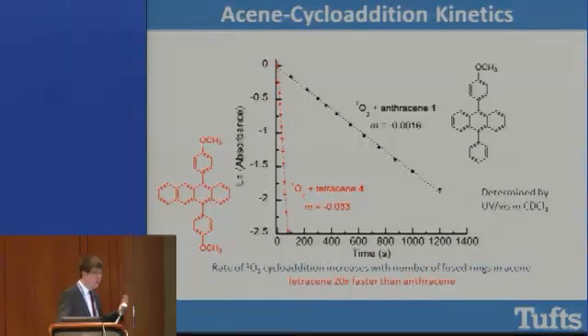So again, just like we do with the furan derivatives, we always want to make sure we understand the reactivity in the products of the reaction between singlet oxygen and our acene units here. And so again, pseudo first order rate law kinetics of both our anthracene derivative pendant and our tetracene derivative pendant show that we see pseudo first order kinetics, as well as a 20-fold increase in rate for the longer acene, which is certainly one thing that you would predict based both on the known chemistry of these acenes. We see a 20-fold increase in pseudo first order rate for our tetracene versus our anthracene, which is one reason we focused on the tetracene substituted polymers. They show a much more rapid response.